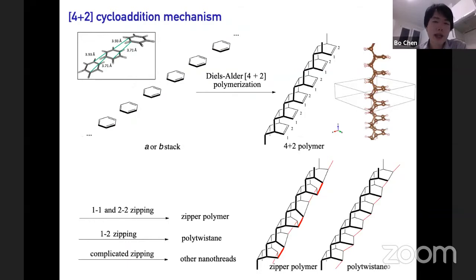So back to the stacks, the parallel stack seems to be compatible with a Diels-Alder 4+2 polymerization, where each ring forms two bonds with the upper ring and two bonds with the lower ring, leading to this 4+2 polymer with one remaining double bond on the same side of a thread. So you can do further reaction for the remaining double bonds, and depending on how you open up the double bond, you can get different types of threads. Importantly, polytwistane can come out from this mechanism.